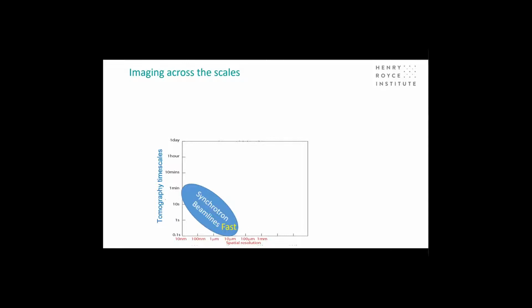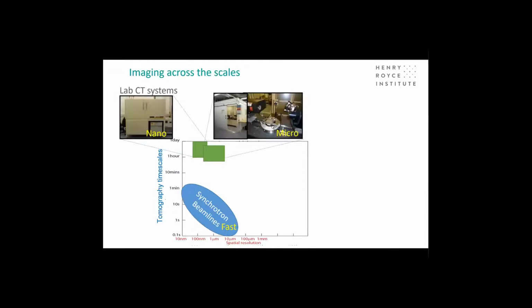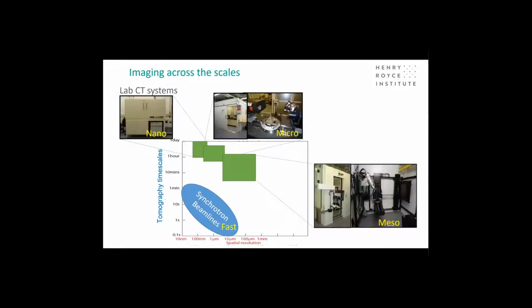Of course, you can also take radiographs, as was shown in the last series of slides, where you can get that individual frame rate. But basically, for fast studies, you tend to need synchrotron beamlines, but for slower studies, you can see here at nanoscale, we have a scanner that will achieve 50 nanometer resolution, but the scan speeds might be 1 scan per day, so much slower than at a synchrotron. Similarly, at the micron scale, it might be a period of hours, and then at the meso scale, where you might be looking at tens of microns, you can do scans certainly in minutes, if not fractions of minutes. And so it does present the opportunity for scanning a range of additively manufactured parts.